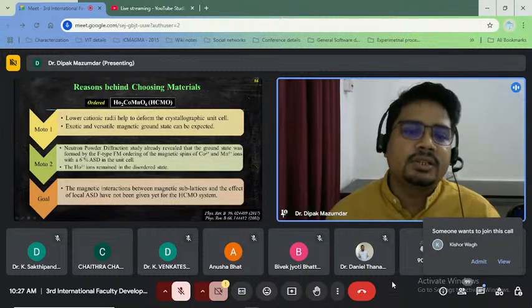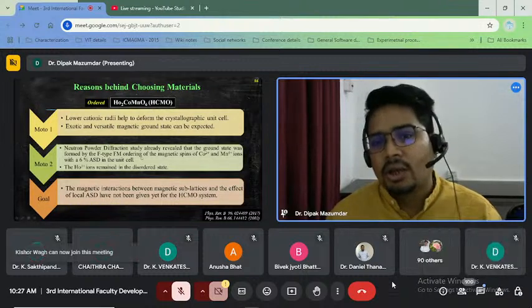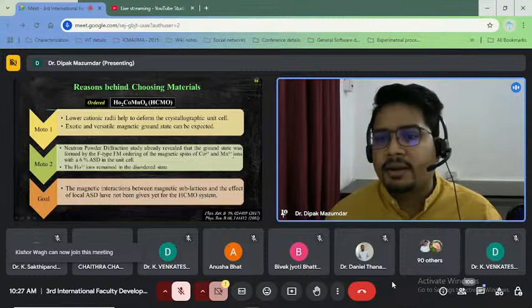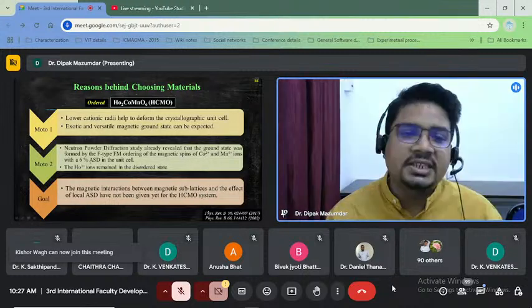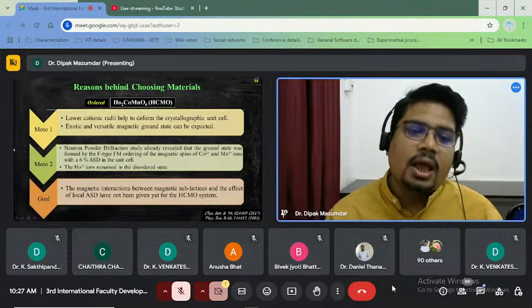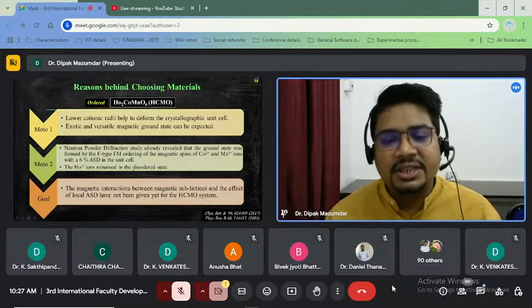Next, in one research paper on this compound, neutron powder diffraction has been performed, and it shows that the ground state is formed by F-type ferromagnetic ordering with magnetic spins of cobalt and manganese 4+ ions, with 6% anti-site defect in the unit cell. And the holmium ions remain in the disordered state.